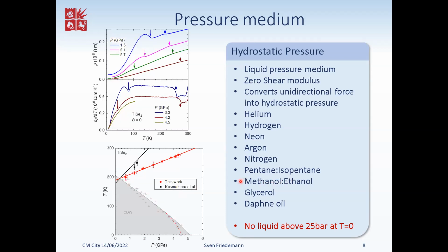signatures are visible in samples that are due to the pressure medium. This is data that I've actually shown yesterday. This is titanium diselenide. Yesterday I drew your attention to the charge density wave transition, but I was not talking about this shoulder here, which is also visible in the derivative. And that's exactly the freezing temperature of the pressure medium.